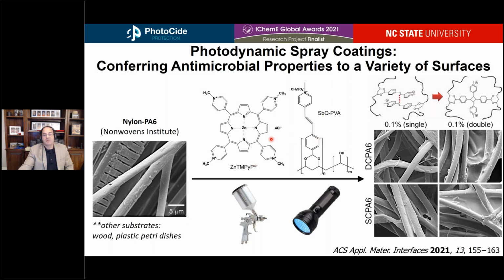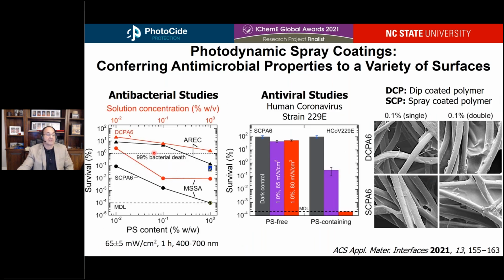This bicomponent mixture, in the presence of UV light, causes a curing photocross-linking of the SBQ-PVA, essentially encapsulating our photosensitizer in a web-like structure that you can see here from the SEM images. We can do this either by dip coating processes or by spray coating processes, encapsulating our photodynamic agent within the photocross-linked SBQ-PVA. Now we can go ahead and take these materials and assess their antimicrobial activity, and that's what's shown here on these slides.